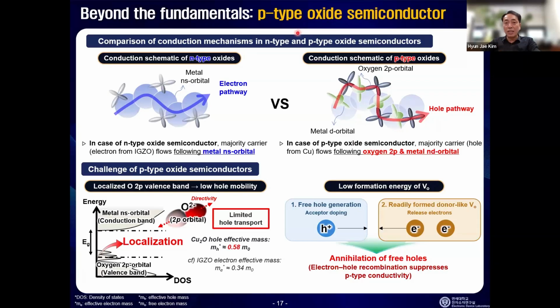Oh, this one is still a blue ocean. Remember oxide semiconductor, I told you, oxygen vacancy is the keyword. Oxygen vacancy means electron. So it's inherently an n-type semiconductor. So people are trying to have p-type with the oxide semiconductor, but most of them failed. See, like, less than 10 papers per year. It's very difficult, I think. I've tried. Cuprous oxide and tin oxide are among the most represented. But I think the reason is, look at this valence band here. This is very localized. It's very difficult.